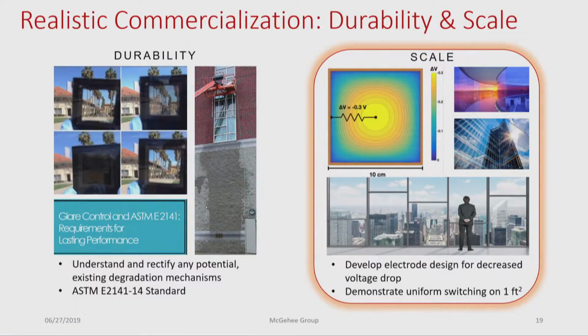So in addition to tackling all the durability issues, we also wanted to focus on scale. On the scale end of things, we wanted to develop an electrode that can minimize this voltage drop that I was referring to earlier. And the most common pursuit to minimize this is to create a TCO with much higher conductivity or much lower sheet resistance. Unfortunately, researchers have been trying to do this for decades, and ITO is getting close to its limit in terms of how conductive it can truly be.